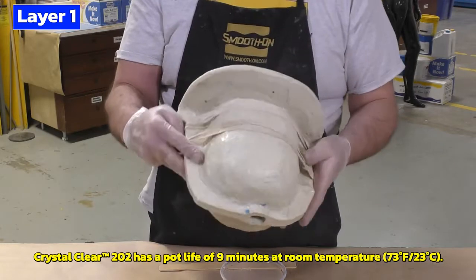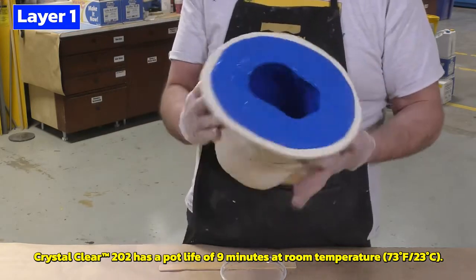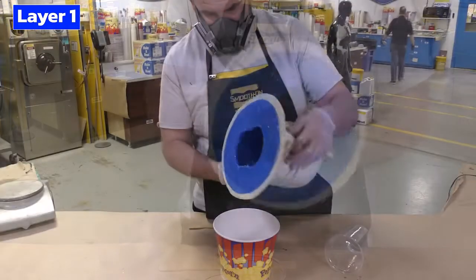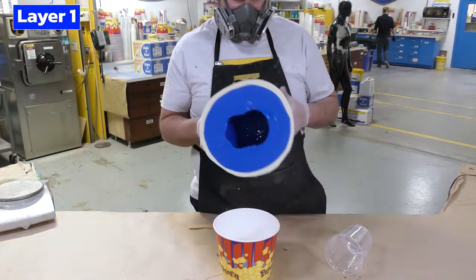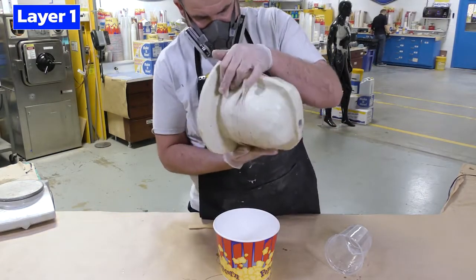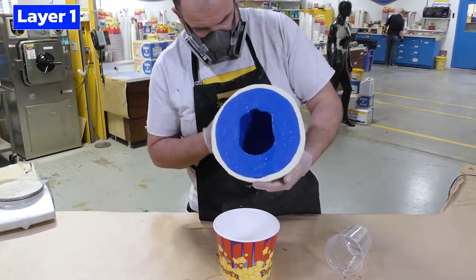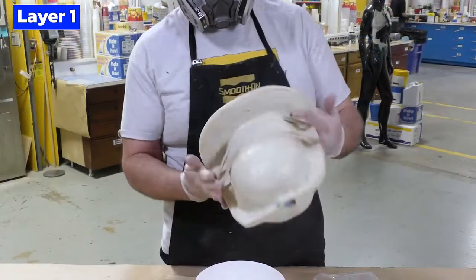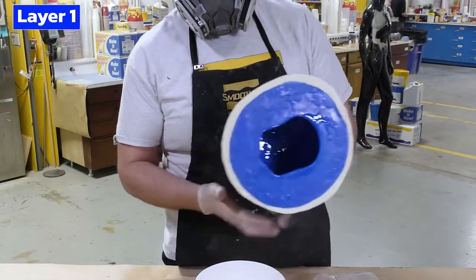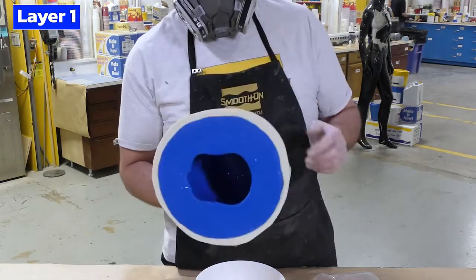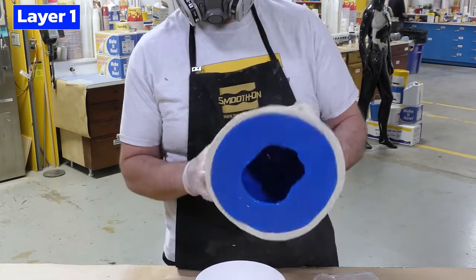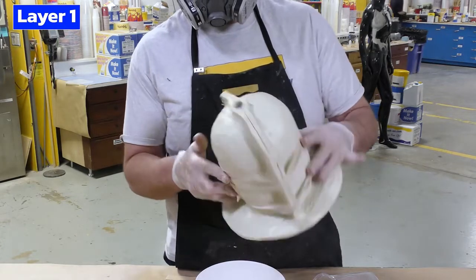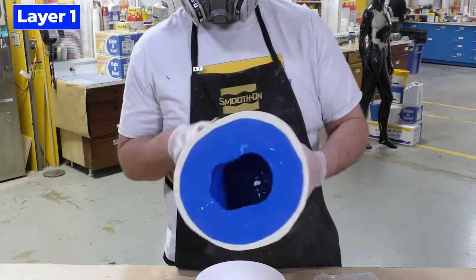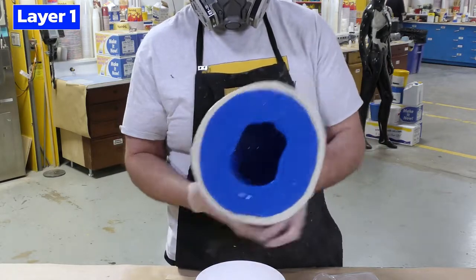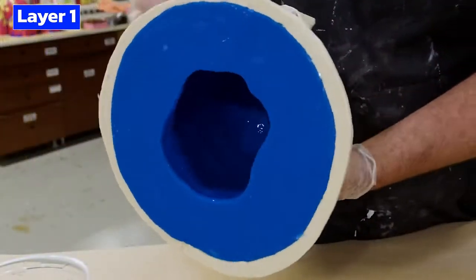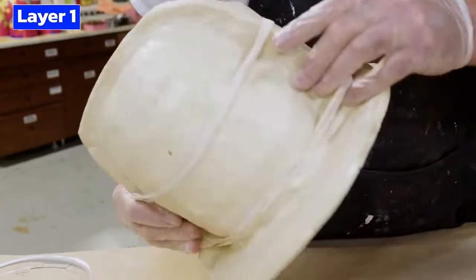So again, keep in mind that because we're using the crystal clear for rotational casting here, we are minimizing the amount of material that is applied to the inside walls of this mold, which is going to also minimize the exotherm of the material, which in turn will prolong the working time of the material itself. So instead of a regular 9 minute working time as per technical bulletin, you can expect more of a 14 to 15 minute working time when it's applied in this manner.